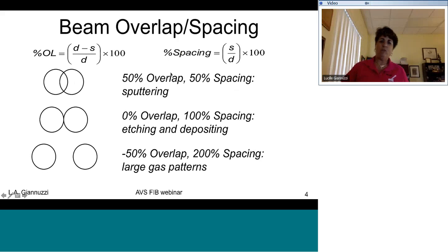So we can define the beam overlap or the spacing or the step size or the pitch size. And of course, if you change one of these things, you automatically change the other. So a 50% overlap or 50% spacing is generally used for sputtering. And here we see what this 50% overlap looks like. At 0% overlap, one edge of the beam is just touching the other edge of the beam. And at minus 50% overlap, this is actually analogous to a 200% spacing. So this is generally used for large area patterns. Again, the 0% overlap is generally used for etching or depositing.